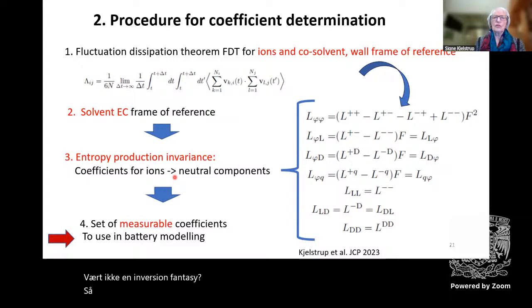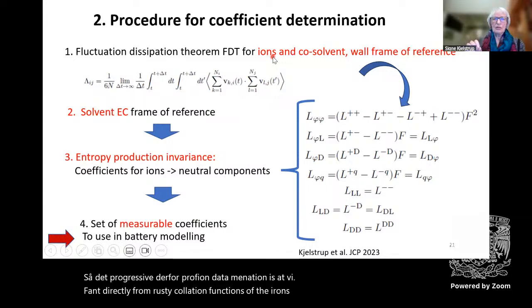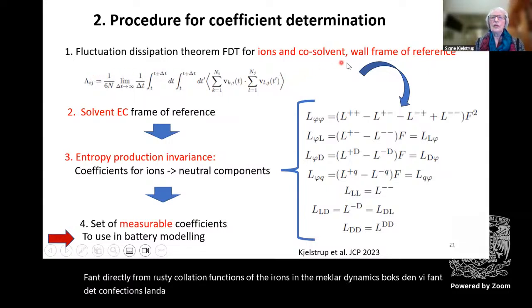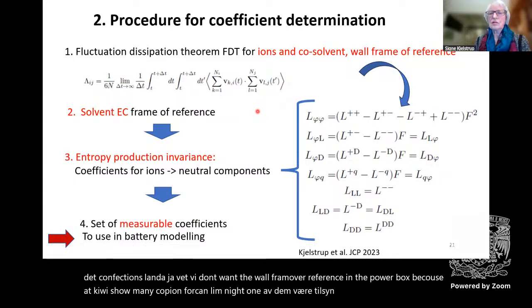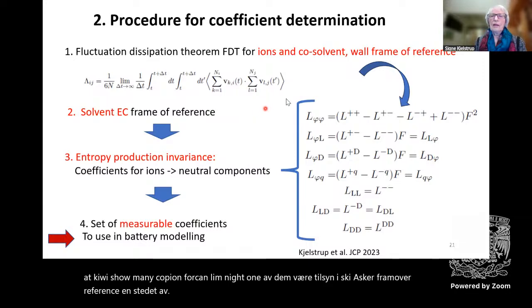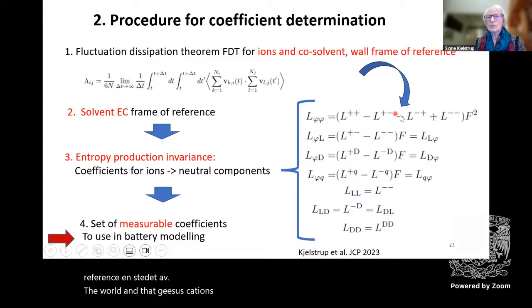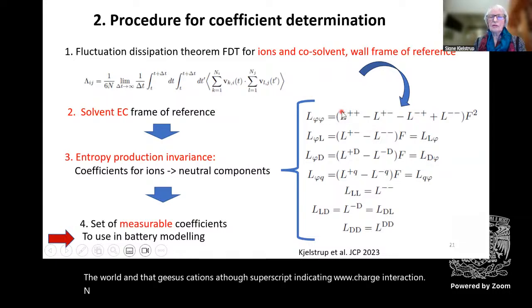So the procedure for coefficient determination is that we find directly from velocity correlation functions of the ions in the molecular dynamics box the coefficients lambda ij. But we don't want the wall frame of reference of the box, because that gives us so many coefficients. We can eliminate one of them by choosing the solvent as a frame of reference instead of the wall. And that gives us the coefficients that have superscript indicating the charge interaction. And from the relation between the driving forces and the others, we obtain the measurable heat fluxes.